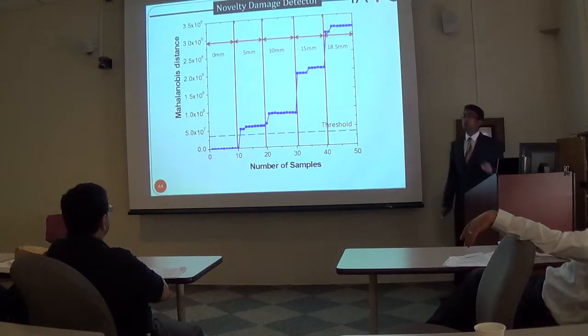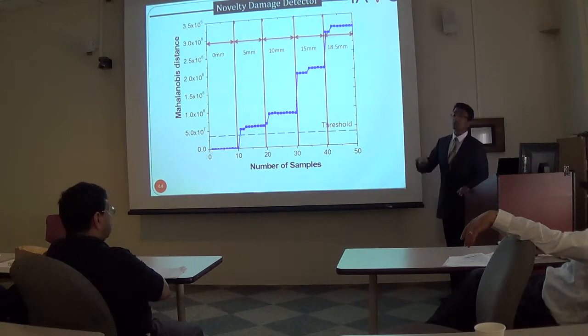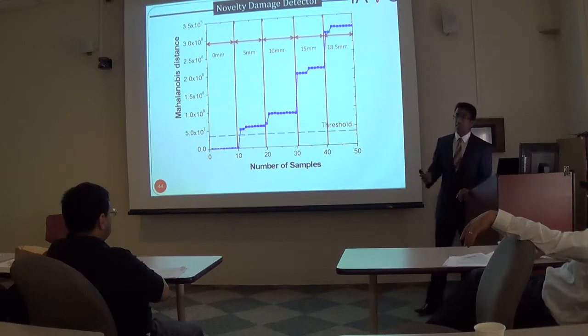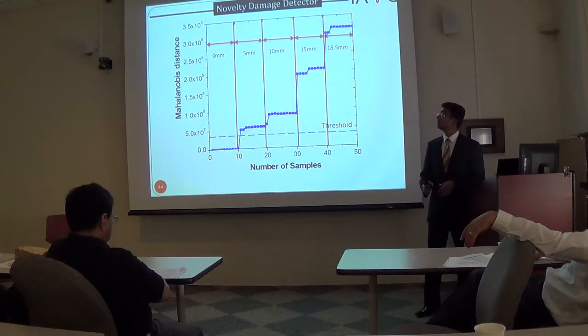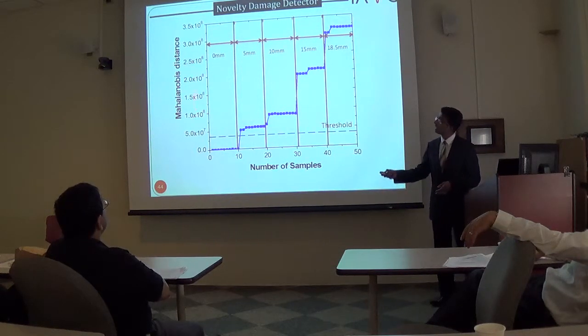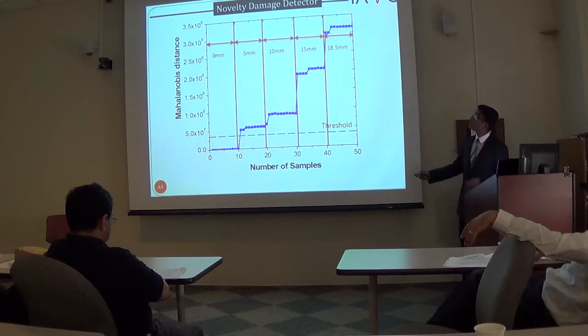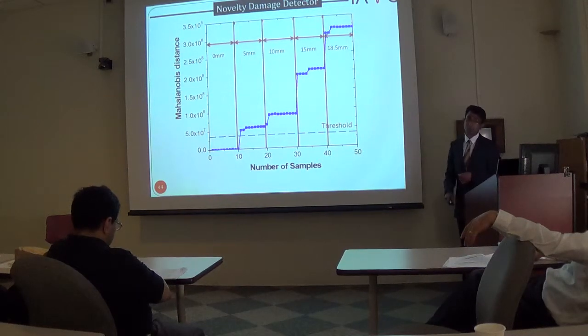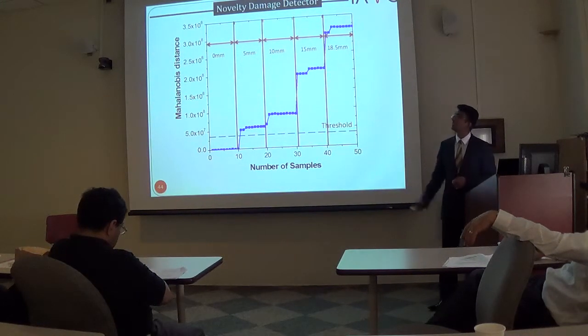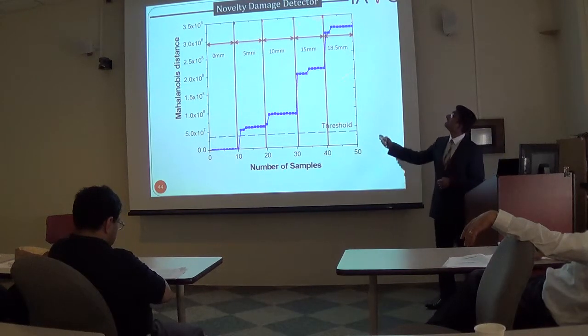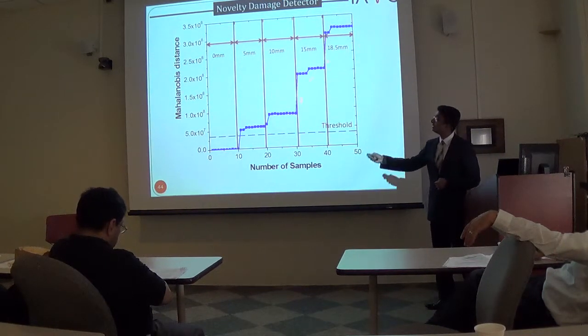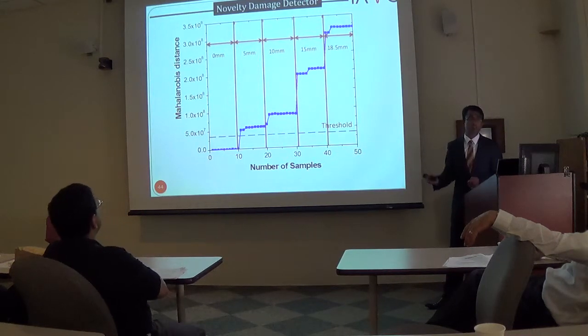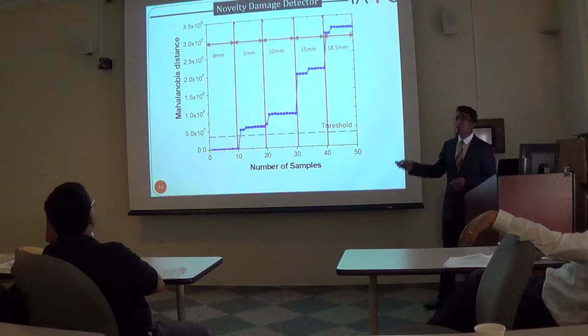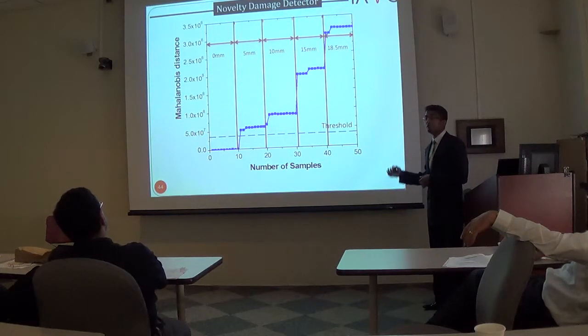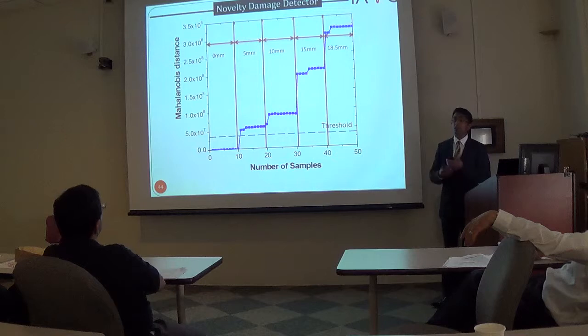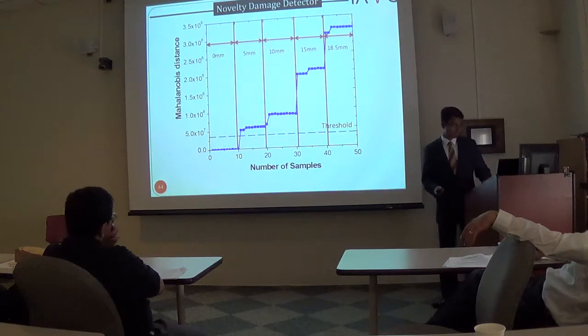So then, in order to validate the identification of cracking and further quantify the crack growth of the material, features that were extracted from the DIC and the acoustic features were then correlated using multivariate analysis such as the Mahalanobis squared distance in order to reliably detect and quantify the crack growth of the material. It can be clearly seen that the Mahalanobis squared distance, which is based on certain parameters, is significantly higher as the crack grows in the material and can be utilized to quantify the crack growth in the material. And also, additionally, you can see that there are very few false positive signals. And thus, this can be utilized as an approach in harsh environmental conditions or field-based applications.